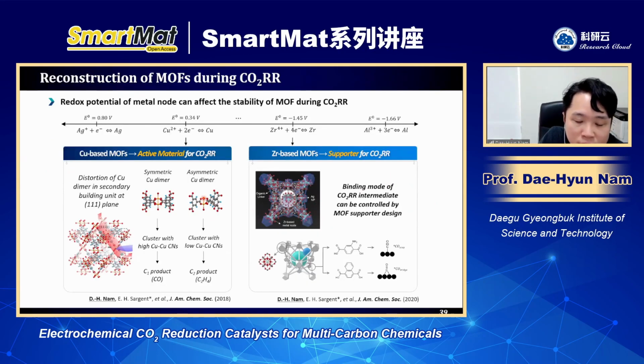So the left-hand side shows the result which I presented before. And on the right-hand side, I think you will remember, although copper undergoes reduction-based reconstruction, this zirconium is very stable. But zirconium is not a good active site for CO2R. In that way, we can use this zirconium-based MOF as a support. And if we incorporate other active materials like silver or copper, then this can be a very good tool to control the microenvironment of the active material.